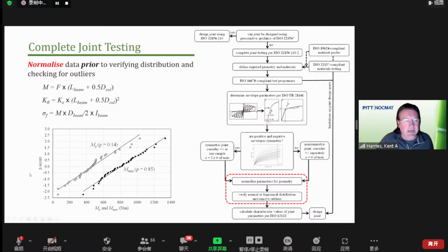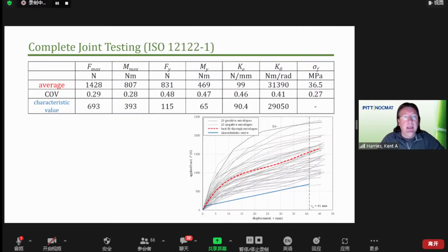And so in this particular case, I'm just showing the distribution, the statistical Z-score versus the two moments, the yield and the maximum. And we see a very nice normal distribution. And we actually do see one outlier down here at the bottom. So we had 40 data points, and so our final data will actually work with 39. We do have a statistical outlier, which wouldn't be surprising in a bamboo test. And so now we can put all of this together.